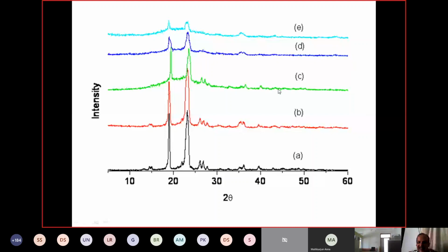So that means its intensity is decreasing and also broadening a little bit. So what's happening? Not only the salt disturbs the polymer, even the nanoparticle is also disturbing the structure of that polymer. That means its crystal nature is decreasing toward amorphous nature. Okay, you also get a clear picture from the DSC plots. You see here, it's for another one where we use the silica material, the nanoform. You see here, the intensity for pure PEO, then as we add it, the intensity is decreasing.